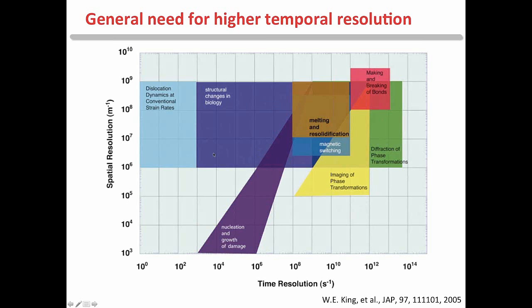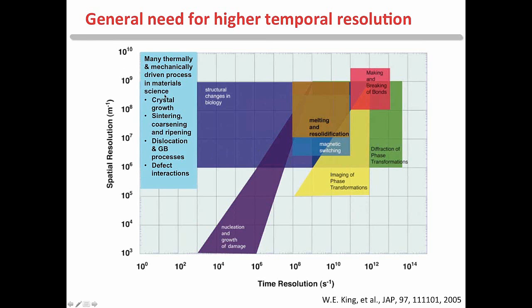But I'd also kind of like to show this because I'm not so sure that it's quite accurate in terms of simply stating that the only thing of interest at the kind of frame rates here are dislocation dynamics. Really, there's a lot more going on. Many thermally and mechanically driven processes in material science, such as crystal growth, sintering, coarsening, and ripening, all the processes associated with dislocation and grain boundary motion and defect interactions are really strongly impacted by the ability to image them at relatively high frame rates down into the milliseconds.